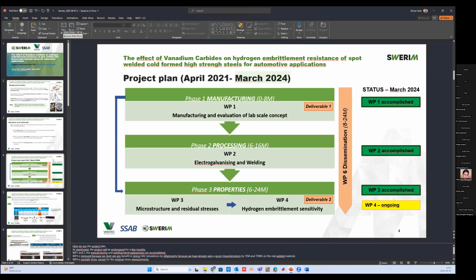This was initially planned from the beginning of the project. The project is ongoing in 3 phases. Phase 1 is manufacturing, where the materials were manufactured at lab scale. The second phase includes processing, mainly electrogalvanizing and welding. And phase 3 includes microstructural characterization and residual stress, as well as hydrogen embrittlement sensitivity. So far, work packages 1, 2, and 3 are completed, and we are still working on work package 4, where we are still evaluating the embrittlement sensitivity.